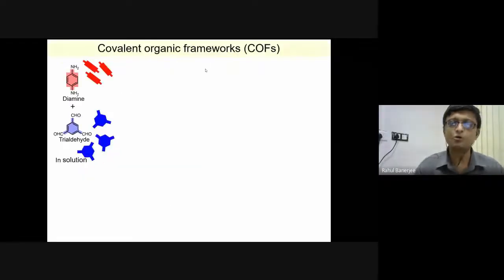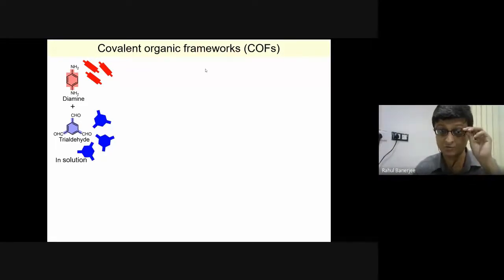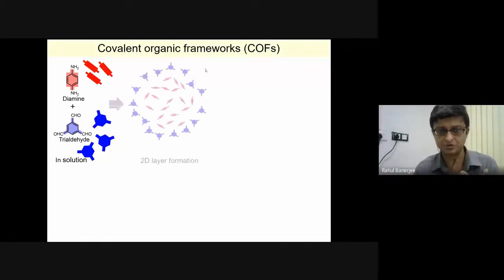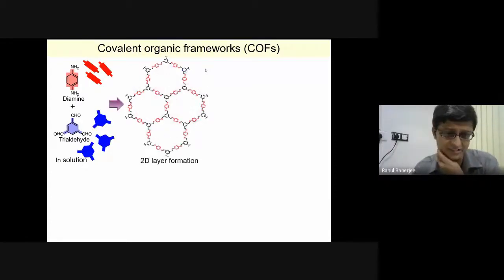So now how we started making it. When we started making it in our laboratory, we took a simple amine and a simple aldehyde. Those who are from the chemistry background know that amine and aldehyde do a very simple reaction called a Schiff base reaction. Hugo Schiff discovered this around 150 years ago. It's a very simple reaction where amine and aldehyde react and you form a C=N bond. Those who are not from the chemistry background can ignore these chemistry jargons.